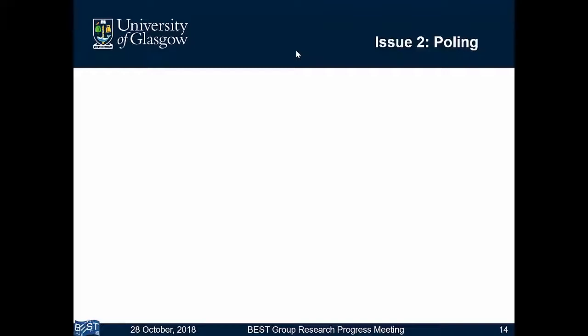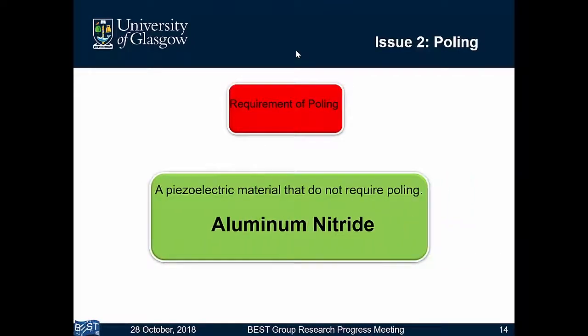So there was a need for another material which can be used as a piezoelectric material over the MOSFET, but that does not require poling. One of the materials was aluminum nitride. The advantage of aluminum nitride is that it has a non-centrosymmetric crystal structure, so there is something in the crystal structure itself which makes it inherently piezoelectric. It does not require poling.